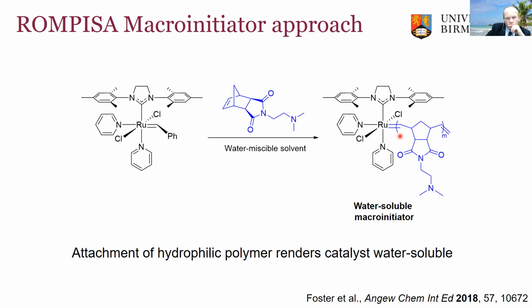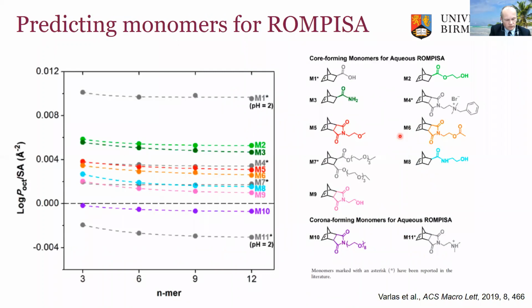So that growth of polymer during polymerization and that transition from hydrophilic to hydrophobic is really key in the PISA mechanism, but it's actually very difficult to know which monomers might do that. So a number of years ago, working with Rob Mathers, we looked at applying a very simple log P over surface area calculation, which allows us to probe how the water solubility of the polymer changes as the polymer grows. And just shown here is the example that we had for the ROMP PISA system.